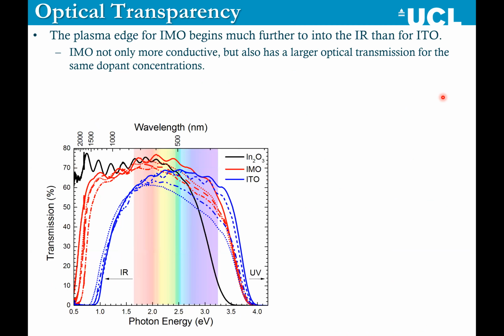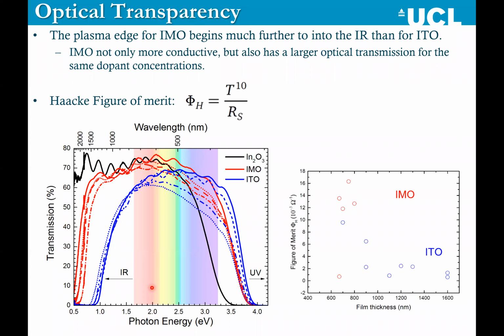So we also looked at the optical transparency of these systems, and what we can see down here is that they're pretty similar in terms of their UV transparency, but in terms of the IR transparency, the IMO samples are much more transparent in the IR. So this is definitely saying something different is happening when you incorporate molybdenum compared to tin. We can calculate something called a Haacke figure of merit, which is simply the transmission to the power of 10 over the sheet resistance. And what we showed was for very thin films of IMO, you could actually get much higher figures of merit compared to ITO.